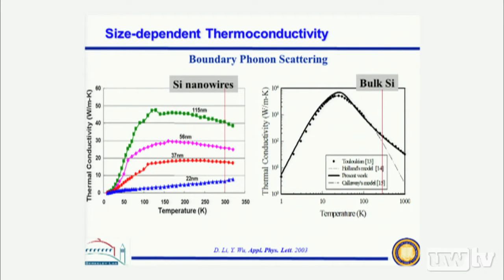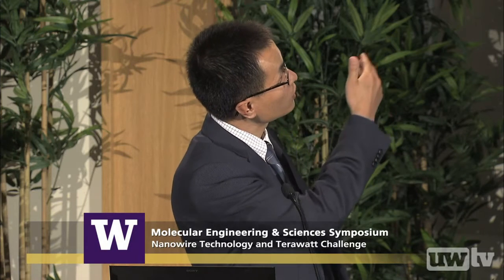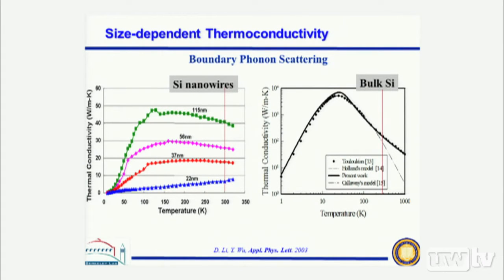During this process, the first thing we explored is the size-dependent thermal conductivity of these one-dimensional silicon nanostructures. If you look at the plot on the right, that's the thermal conductivity for bulk silicon. If we look at the data for room temperature, we're talking about a couple of hundred watts per meter Kelvin. So that tells you bulk silicon is a very good thermal conductor. It's never going to be a good thermoelectric. Now, if you reduce the dimension of the silicon nanostructure from 100 nanometers down to 20 nanometers, you immediately notice that thermal conductivity can be suppressed to below 10 watts per meter Kelvin. So you are designing nanostructures that suppress thermal transport, and that's the beginning of how we can really design nanostructured semiconductors to develop better thermoelectrics.